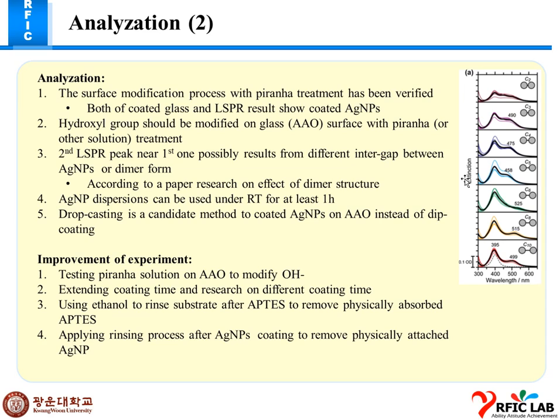The surface modification process with the piranha treatment has already been verified, because both the coated glass and the LSPR results showed coated Ag nanoparticles. The hydroxyl group showed modification on the glass surface with the piranha solution, and the second LSPR peak near the first one possibly results from a different intergap between the Ag nanoparticles or dimer form. The dispersion can be used at room temperature, with at least 1 hour for the Ag nanoparticle onto the surface, and drop casting is a candidate method to coat Ag nanoparticle on AAO instead of dip coating,